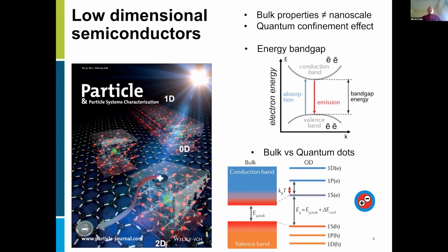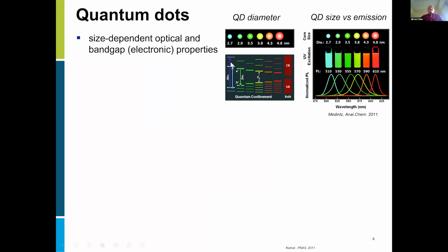What does it mean in terms of electrical and optical properties? It means that quantum dots in particular will show size-dependent optical and electronic properties. If you look at this figure here, we have a series of quantum dots where we change the size from something like 5 nanometers all the way below 3 nanometers. If you look at the band gap of this material, the difference between the valence band and conduction band, this band gap enlarges with a decrease in the size of the quantum dot. What does that mean? We need more energy to create electron-hole pairs when we decrease the size of the quantum dot. And this energy increases as compared to the bulk counterpart.